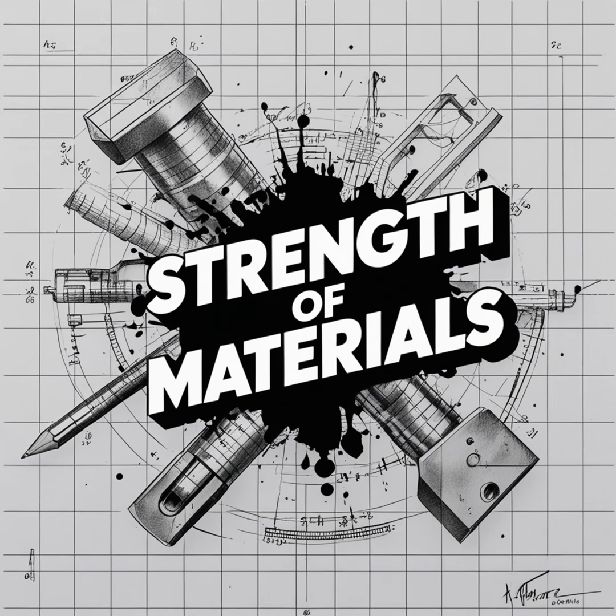Precisely. And this is vital because when glass is loaded in tension, like when a rock hits, your windshield failure almost always initiates from microscopic flaws on the surface. But for tempered glass, before the impact force can even begin to exert a tearing, opening load on those surface cracks, it must first completely overcome that massive, built-in compressive squeeze. It's like having a heavy-duty rubber band wrapped as tightly as possible around a block of wood. Before you can pull the wood apart, you first have to pull hard enough to defeat the squeeze of the rubber band. That's why tempered glass can sustain such massive impacts before shattering.